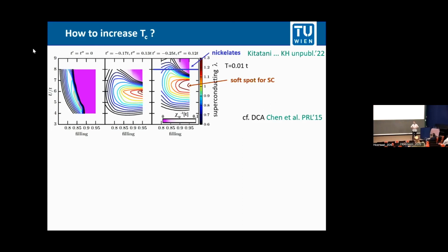So if the antiferromagnetic fluctuations are large, we are far away from a quantum critical point here yet, then the pseudogap wins. It's also a non-Fermi liquid phase, but of course a different one than that close to the quantum critical point. And that has been well known before, that with strong antiferromagnetic fluctuations, you get a pseudogap, and this large scattering at the pseudogap in these regions at finite temperature suppresses superconductivity. That is what we find here. And I think this deformation of the fingerprints shows very nicely how antiferromagnetic fluctuations suppress superconductivity, and that T prime equals zero is particularly bad.